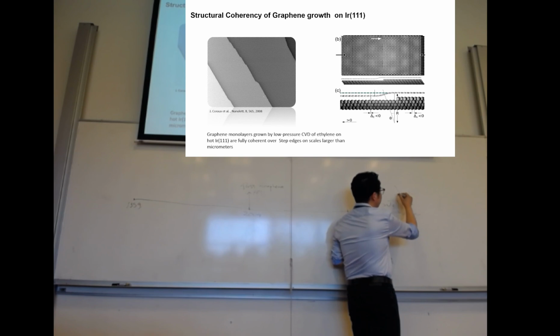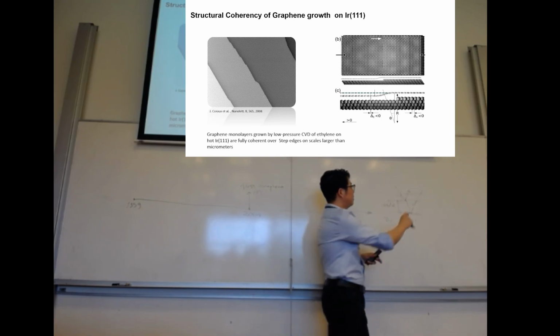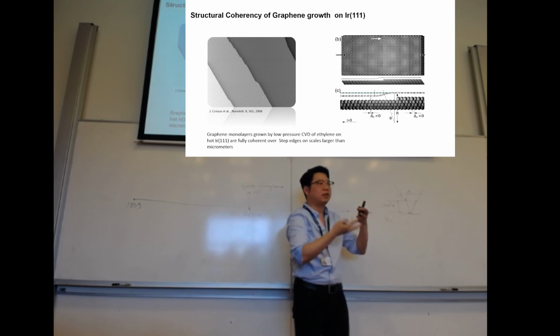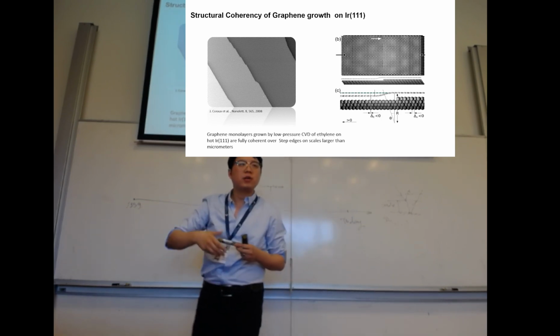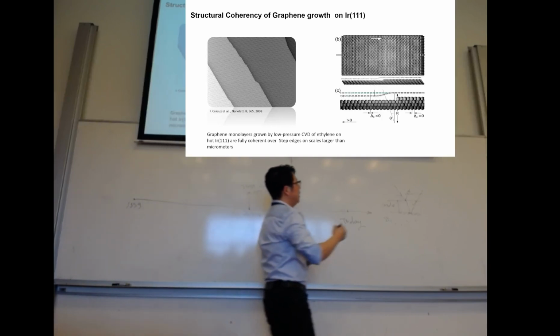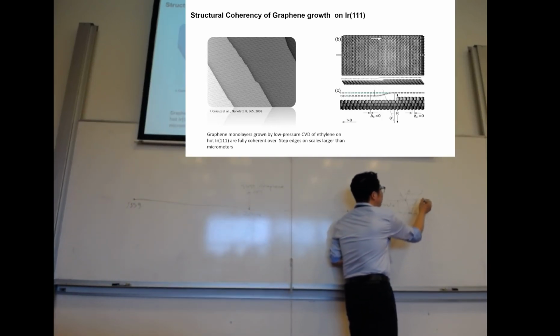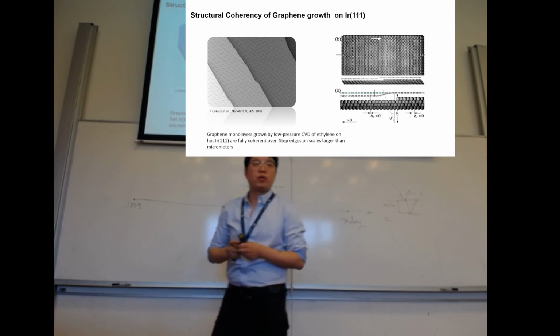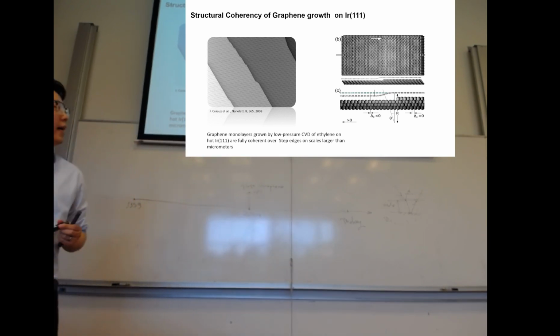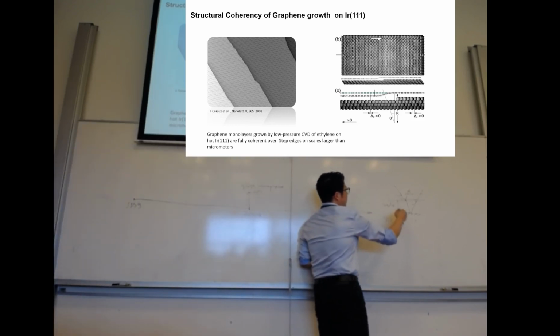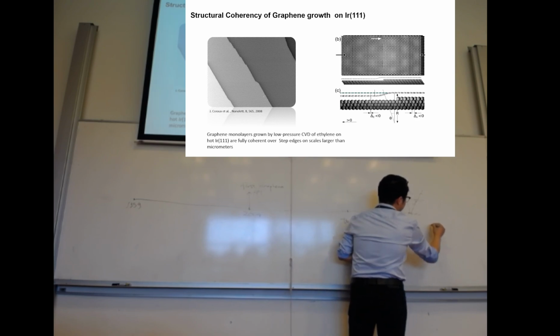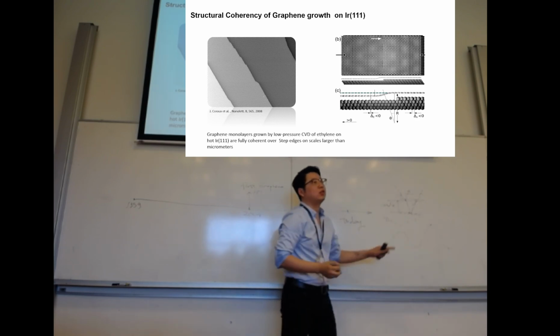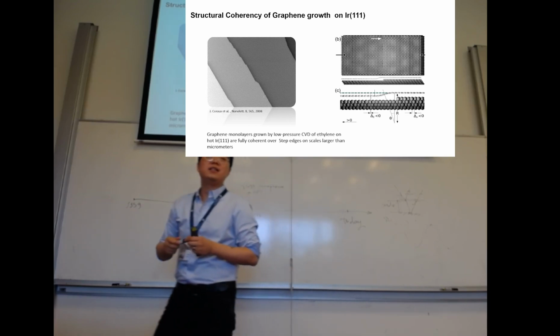The light comes down, and then you get twice the reflection. There is some condition where you have constructive and destructive interference of the light, and plus there is a thin film of graphene on top. So the absorption is about 2.3% per layer. And if this is really one layer, at some point, if you have destructive interference, you don't see it. The visibility is really low.